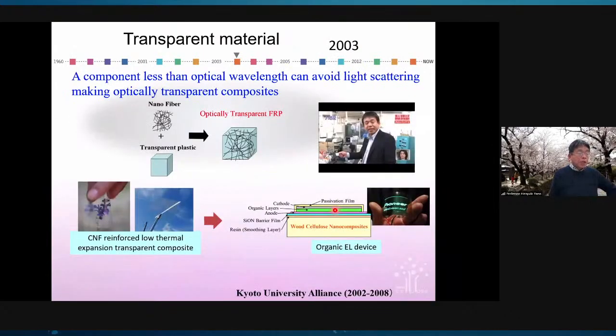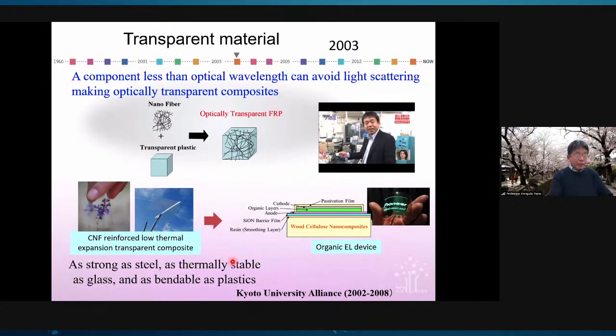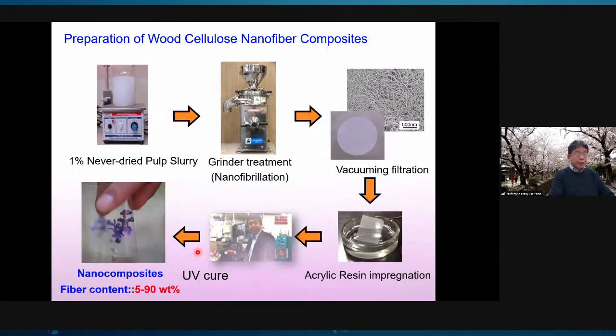And in 2003, we developed an optically transparent and low thermal expansion cellulose nanofiber composite. The composite is as strong as steel, as thermally stable as glass, and as flexible as plastics. This is the preparation process of the optically transparent composite. At first, we prepared a CNF sheet by vacuum filtration of CNF aqueous suspension, then impregnated it with acrylic monomer to get rid of air inside.